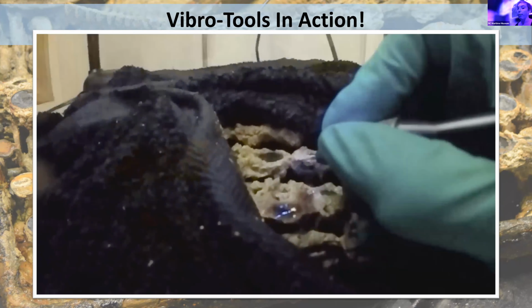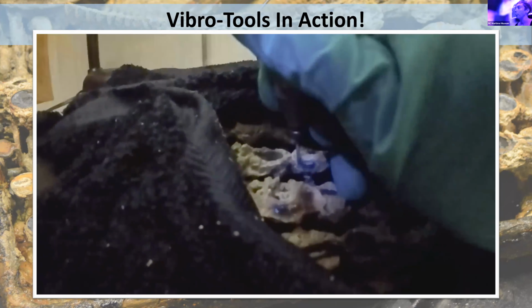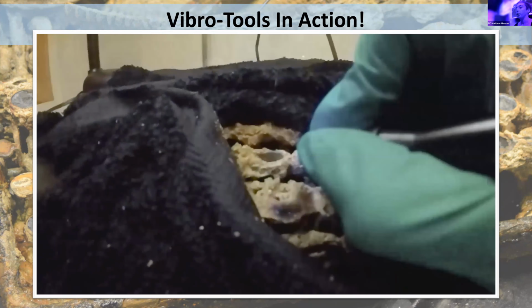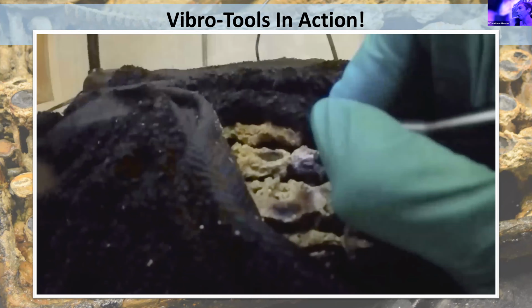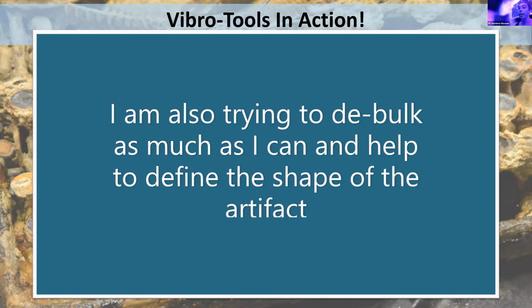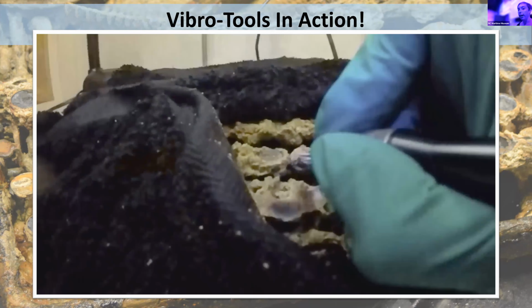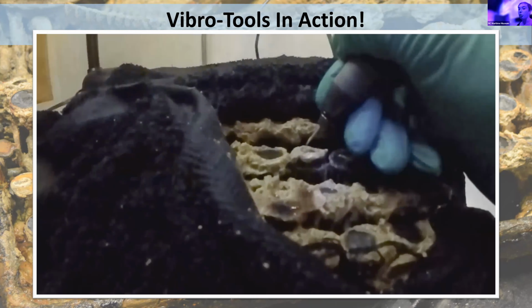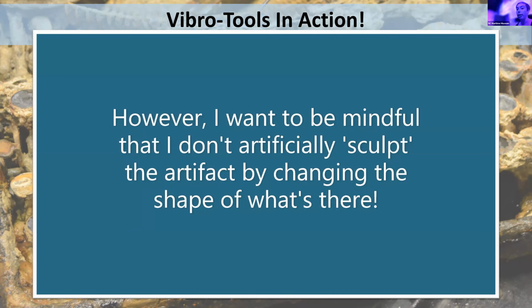If there's any surface detail like inscriptions or maker's marks, or graffiti, for instance, a lot of that material is actually retained in the most proximal layers of corrosion, the layers that sit most closely to what would have been the surface of the artifact. They've kind of replaced that surface and keep a lot of that detail. So you have to be careful when you're removing this material that you don't accidentally destroy that detail.